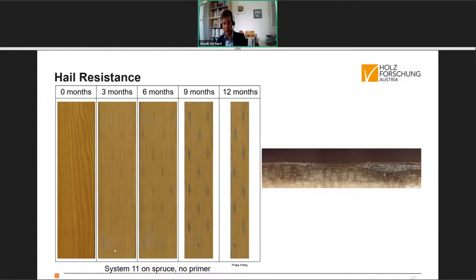And you see what hail does to a coating. This is hail simulation on a weathered surface at the beginning of weathering, and then during weathering you see continuous degradation around these hail impacts. And this is a microscopic image of a longitudinal section through a hail impact, where you see a lot of discoloration and fungal growth around this hail impact.